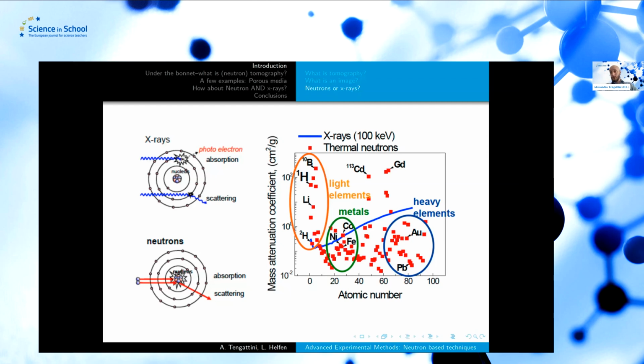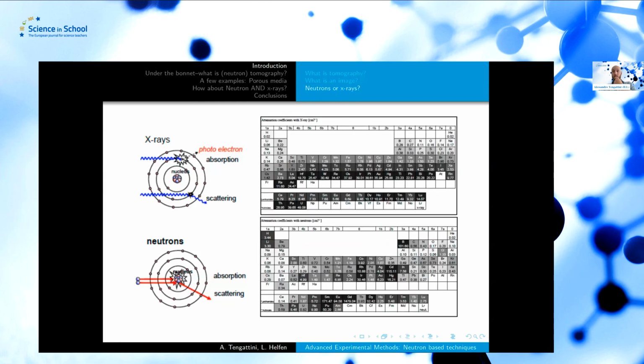Now, in the case of neutrons, this is not as intuitive because the neutrons will interact with the nucleus of the atom. So you have very light elements such as hydrogen and boron, which are very transparent to X-rays, and they're very opaque to neutrons. And vice versa, you have very heavy elements such as lead, which are almost transparent to neutrons. So it's a bit less intuitive, and we'll get more in detail to why and when we can exploit this interesting difference.